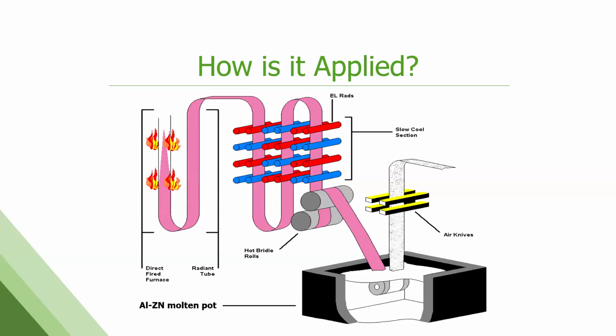So we're actually impinging open flame on the strip in the first part of the furnace. Then it goes through a set of electric heated and cooled rollers to anneal the product. We have to cool that strip down before it hits the pot of molten metal. That's really critical. The temperature of the strip and the temperature of the molten metal have to be just right, or you don't get the formation of this metallic coating onto the steel.